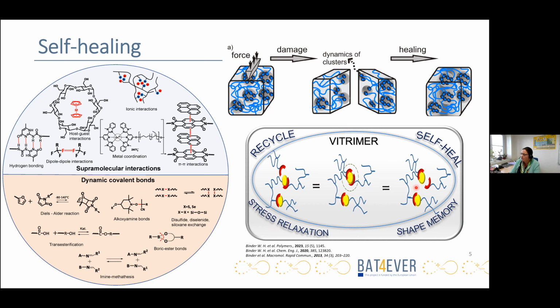The control of this equilibrium, which is here schematically presented, can be triggered by different stimuli like irradiation, pH value, moisture, catalytic activity, and temperature. Temperature or heat is the most used trigger because it's easily tunable and of course relevant for different applications.